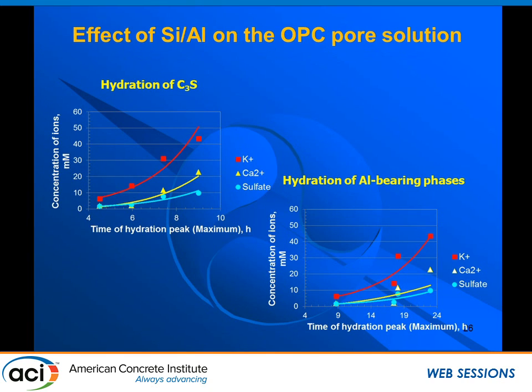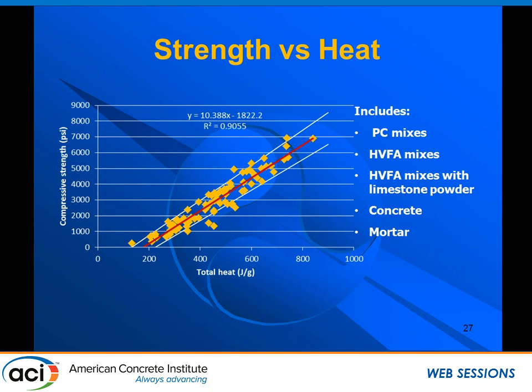So is there any relation between the concentration of ions and the time that peaks appear? For the silicate peak, yes, it's very clear that there is a relation between concentration of ions and the time the peak appears. For the aluminate peaks, there is some correlation, but not as good as with the other peak.